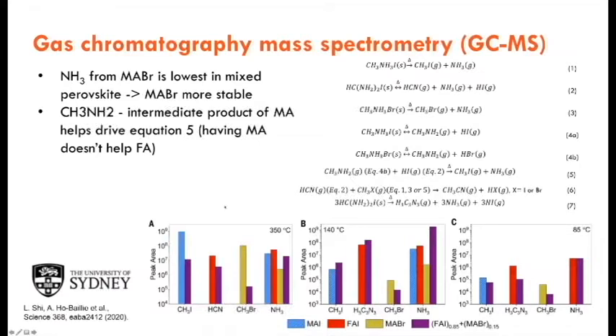So you can see that the ammonia is lowest for MABr. And what it says is MABr is more stable, and we do find that. So if we mix MAI with MABr, in very early research, maybe 7 years ago, people found that it stabilized the perovskite cells. And also methylamine comes out as an intermediate product. As a very small amount, it can't be detected. But what is important is it comes out of the MAI, and having that actually will react with the product of the FAI and then drives the decomposition reaction here at 5. So if you don't have MA, the FA type perovskite is quite stable.